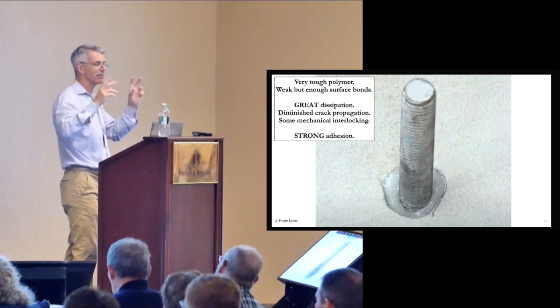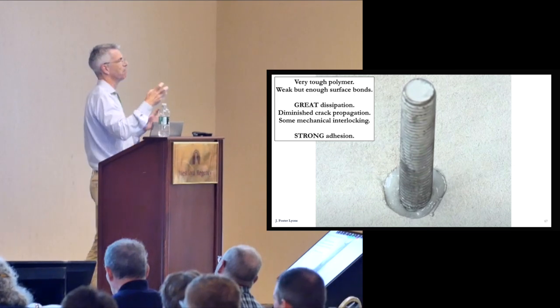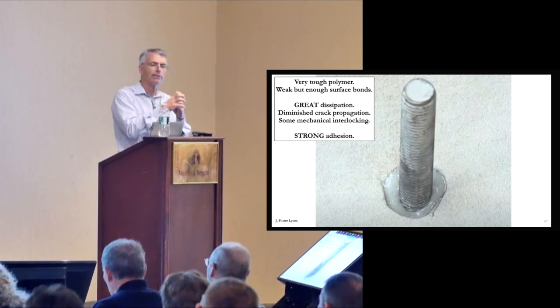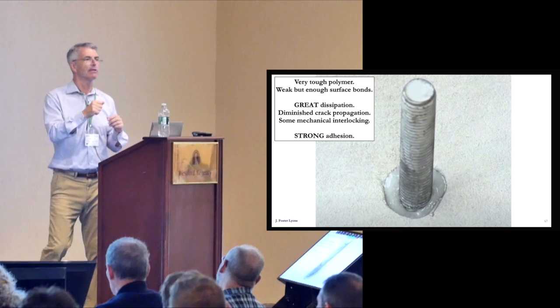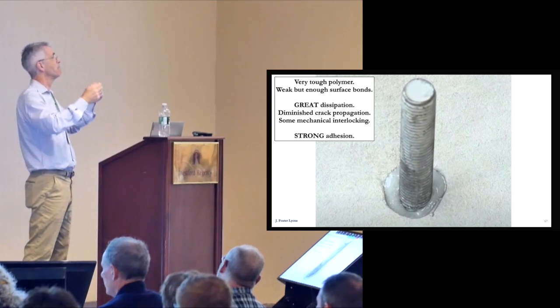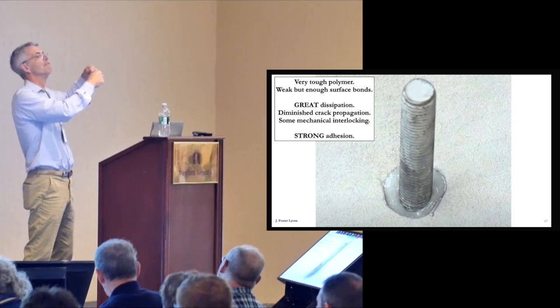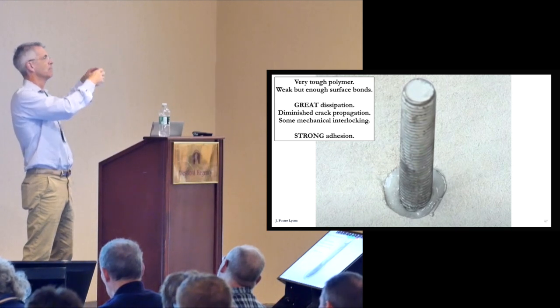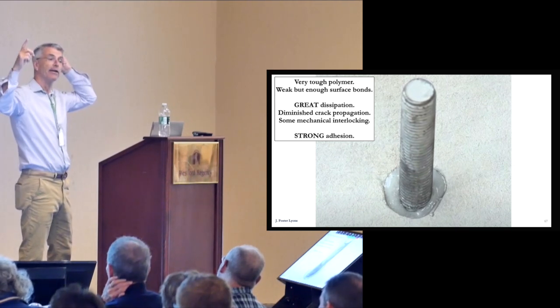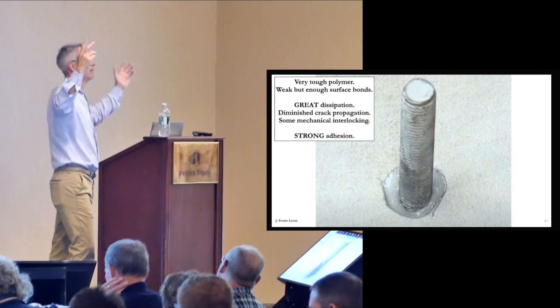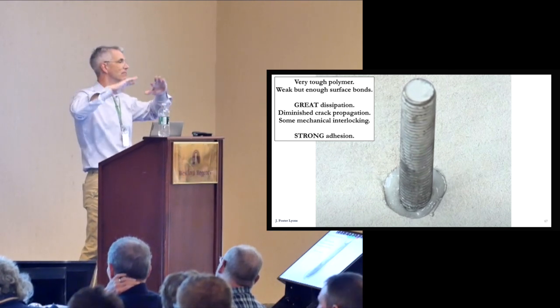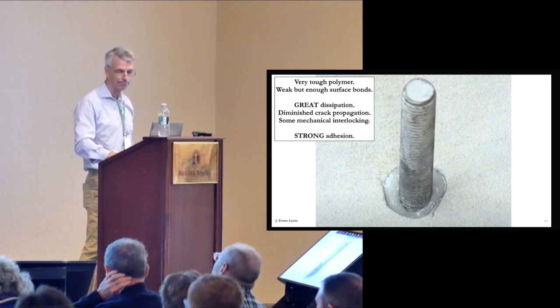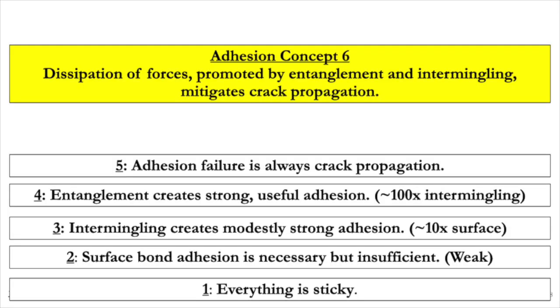With these kinds of bolts, there's also a tiny bit of mechanical interlocking, and because the polymer is so tough, it can kind of get stuck there. But it's really the polymer doing the work for you by dissipating the forces. Even if a crack starts, which would normally continue at the speed of sound, like your windshield breaking, it gets dissipated into the material, and that absorbs all the energy, all right? So that's adhesion concept 6: dissipation of forces promoted by entanglement and intermingling mitigates crack propagation. And number 5 right below it says adhesion failure is always crack propagation.